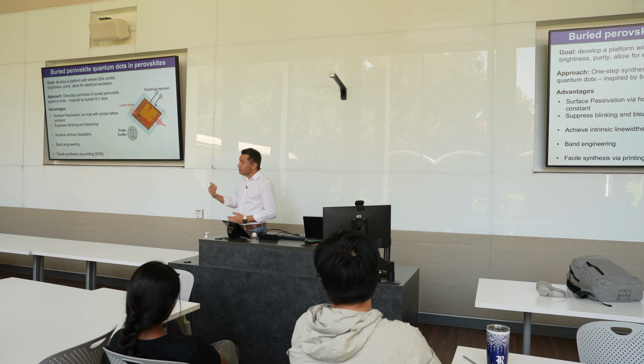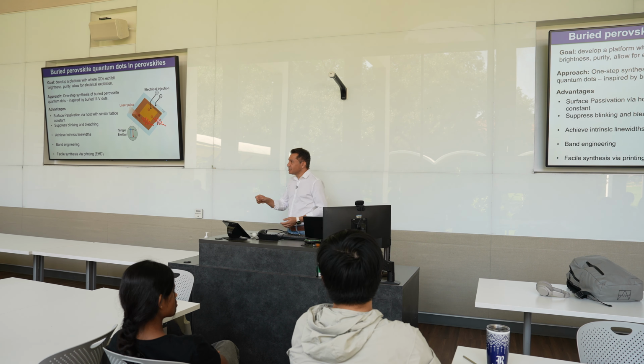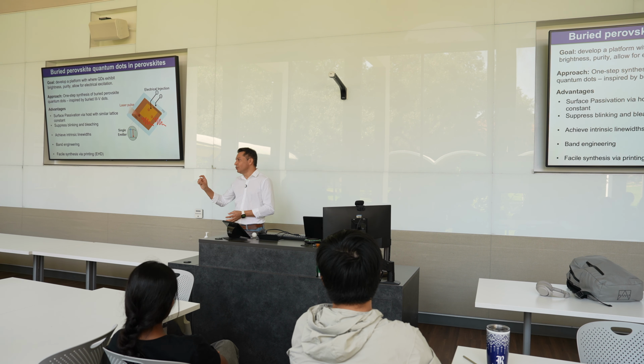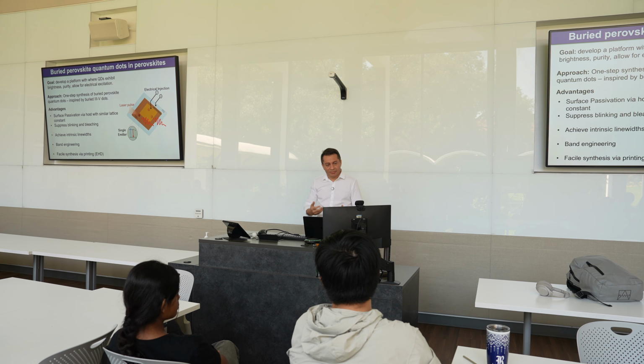In perovskites, it's even more sensitive. In the colloidal II-VI systems, cadmium sulfide, cadmium selenide, they put a cadmium sulfide shell. Moungi Bawendi got the Nobel Prize for trying to get these, and they make LEDs out of it. In perovskites, it's even harder because I told you it's a soft material. Imagine it's like cotton wool, like a cotton ball, you've seen those cotton balls. Try to do some chemistry on that. It's very hard. Even if you manage to put some ligands or some kind of shell on it, it doesn't remain stable because it's very, very soft. So that's an issue, and we wanted to overcome that.